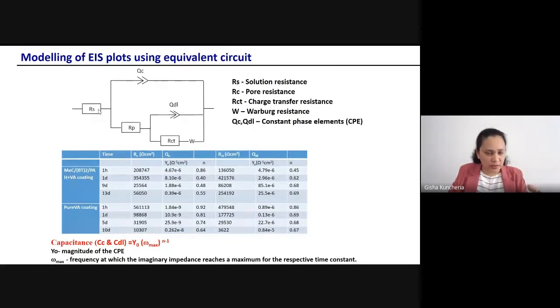This is an equivalent circuit used to model this Bode plot. Here, RS means the solution resistance, and there are two circuits connected in parallel. The first circuit, QC and RP, corresponds to the polymer coating. QDL and RCT correspond to the corrosion on the metal surface. So solution, then coating, then metal. In the same way, we applied this, and the best-fit parameters of this modeling are given in the table. From here, you will get the idea about what is the resistance of the coating, what is the capacitance of the coating, and what RCT, the charge transfer resistance, that is the corrosion resistance, is being provided. All this information you can get from this modeling of the EIS plot.